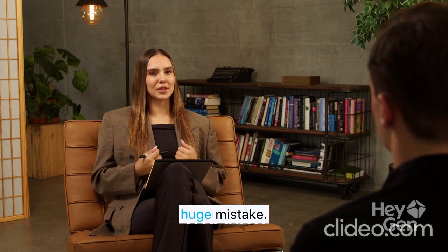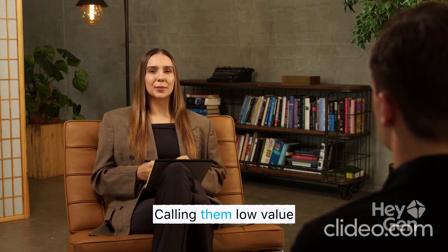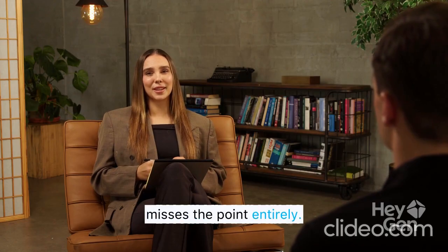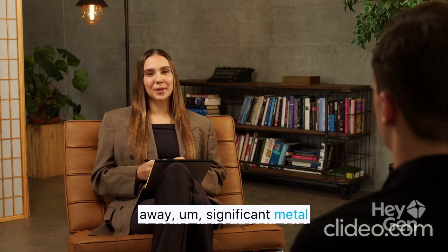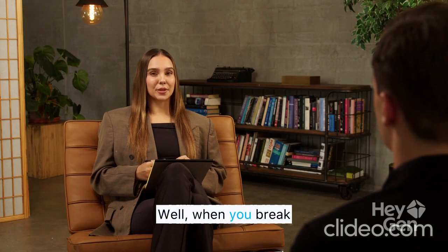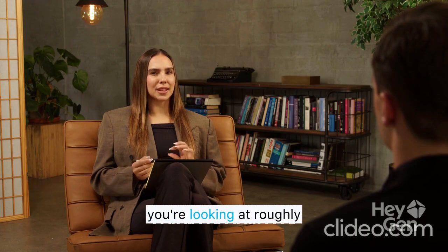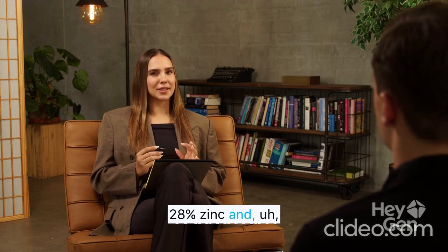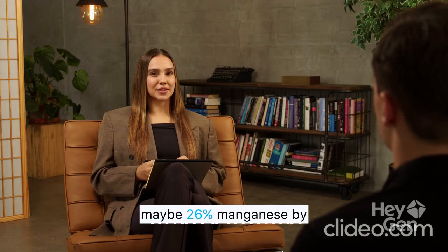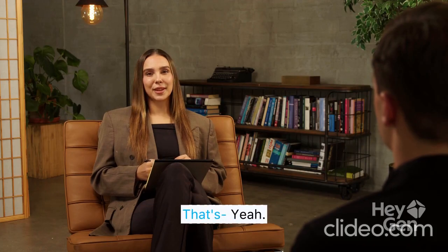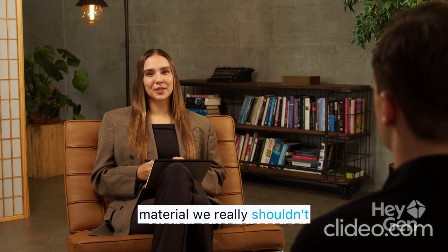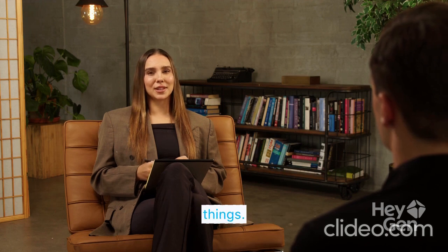Which is honestly a huge mistake. Calling them low value misses the point entirely. We are literally throwing away significant metal assets. Really? What's actually in them? Well, when you break down a spent one, you're looking at roughly 28% zinc and maybe 26% manganese by mass. That's a lot of material we really shouldn't be putting in the landfills. Wow, okay, that changes things.